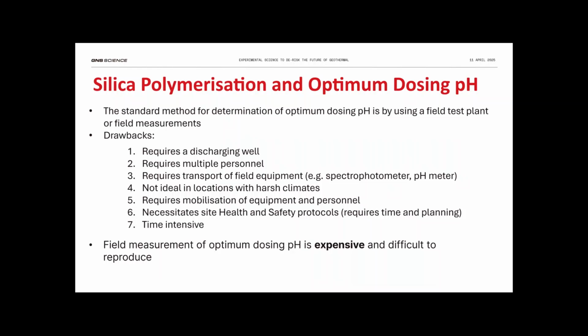So the standard method for determining optimum dosing pH is by either a pilot plant, a field test plant, or doing field measurements. The drawbacks of this is that it requires a discharging well because you need fresh brine from the ground. It requires multiple personnel, requires the transport of sophisticated equipment like spectrophotometers. It's not ideal in locations with harsh climates. It requires mobilization of equipment and personnel, particularly if it's overseas and you don't have the equipment on site. It necessitates involved health and safety protocols for doing field work in a steam field. And clearly all this becomes time intensive. So the field measurement of optimum dosing pH is expensive, and it's difficult to reproduce results in the field because of all these factors involved.